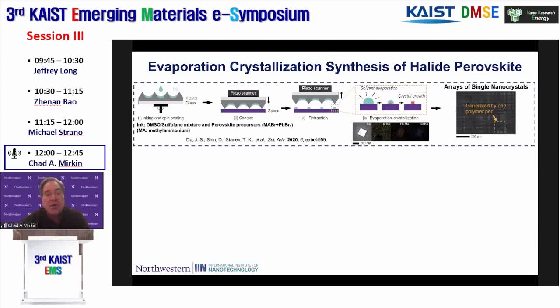So one of the things that we thought would be interesting is, could we learn how to make, for example, perovskites, halide perovskites? Well, you can't make them with the conventional polymers that I talked about, but you can take DMSO sulfolane mixtures and use that as your solvent in your reactor generation. And you can put your perovskite precursors in those, load them up on the polymer pen arrays, and now begin to use polymer pen lithography to print out literally millions of reactors. And in each of those reactors, you can initiate the reaction that leads to the halide perovskite.